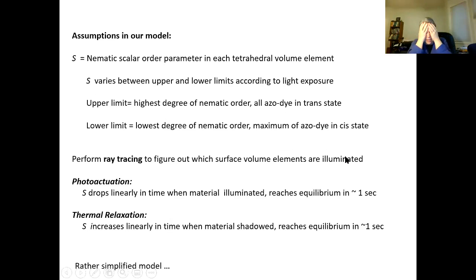We said, okay, we know there's this complicated photochemistry, but let's boil it down to something super simple. Let's imagine that the scalar order parameter drops linearly in time when the material is illuminated, going from some highest value to some lowest value in about 1 second. And if you take the light away, S relaxes back to where it was in about 1 second. So it's a really simplified photochemistry model. We'll just let the scalar order parameter have a highest value and a lowest value, the most ordered it can be and the least ordered it can be for that much light. Of course, that would depend on the light intensity and the temperature, but we wanted this big, simple model to be able to run in a finite amount of time.